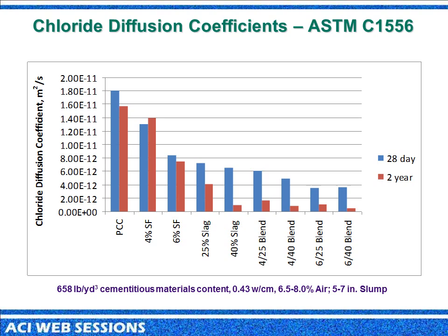We had done the testing using the regular testing protocol, which is at 35 days ponding. However, no ions were really getting in at any substantial depth. So we had to go back and retest those, and we ponded them for 70 days. We found, again, we're not getting enough chloride into the samples to really look at what we're trying to get at, which is the actual diffusion rates. So what we finally did for our 2-year is that we actually ponded the specimens 140 days. Now, this is 4 times the testing protocol. So you can see by using both the slag cement and also the silica fume that we've created an extremely dense structure which would increase the durability substantially.